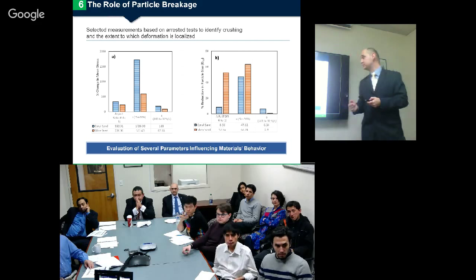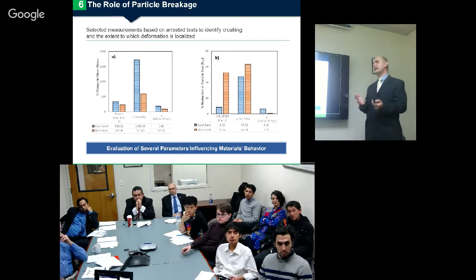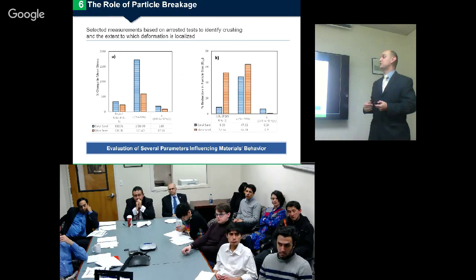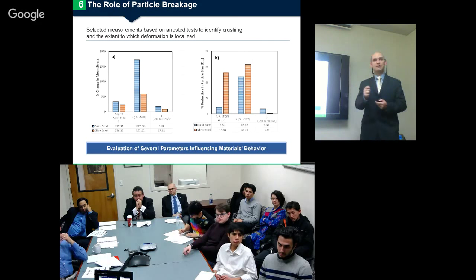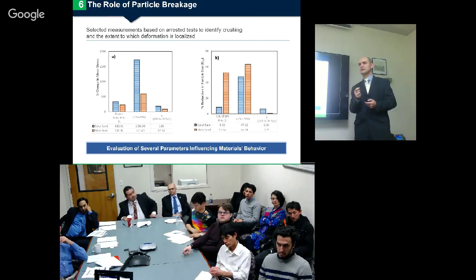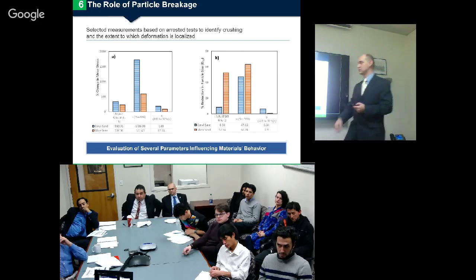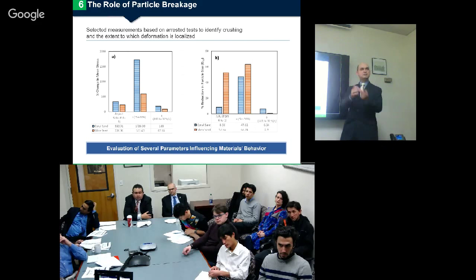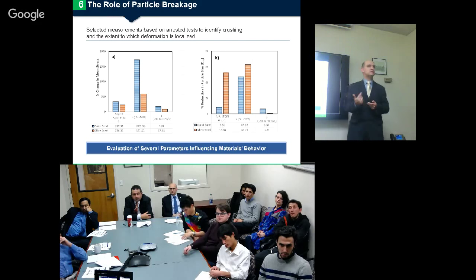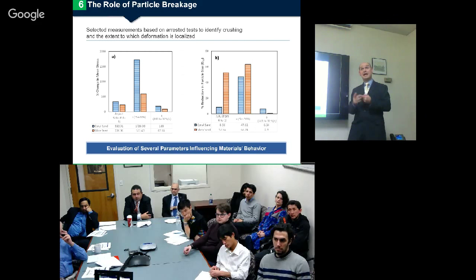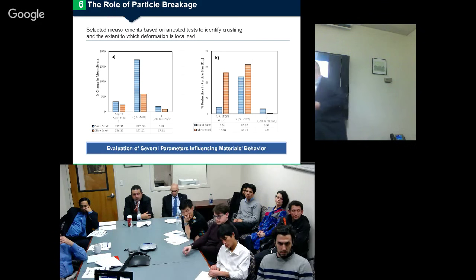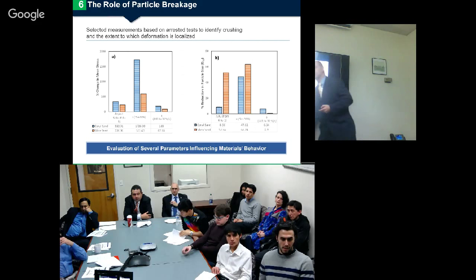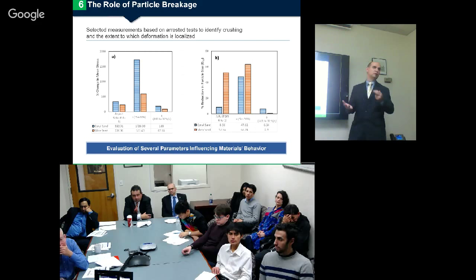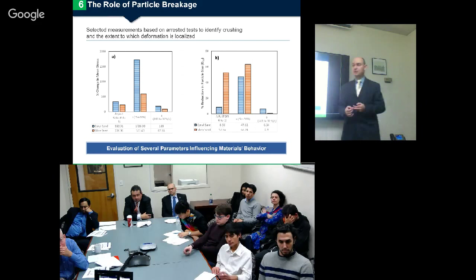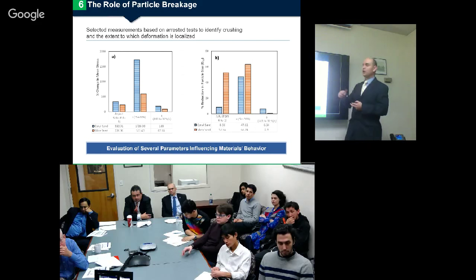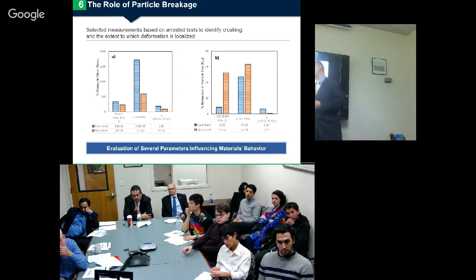And also at the end, by using a simple analysis of variables, I wanted to identify what variable influences more in both main conditions: the change in the mean stress of this stress-strain curve and the change in the particle size. So how the particle size reduces, and what variable is more influential? So we have aspect ratio, obviously. We have axial deformation, or again, it could be porosity, it could be void ratio. And we have a strain rate from 0.01 to 10% per second on both materials, calcareous material and siliceous material.